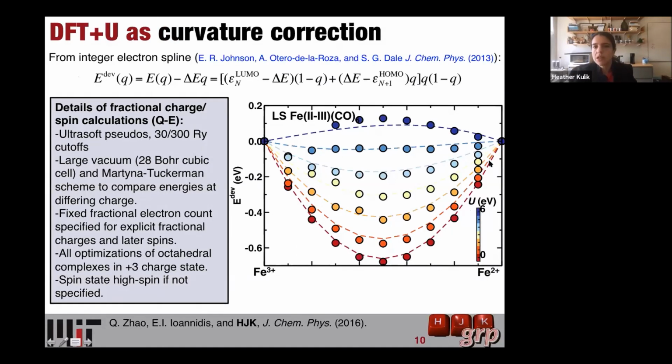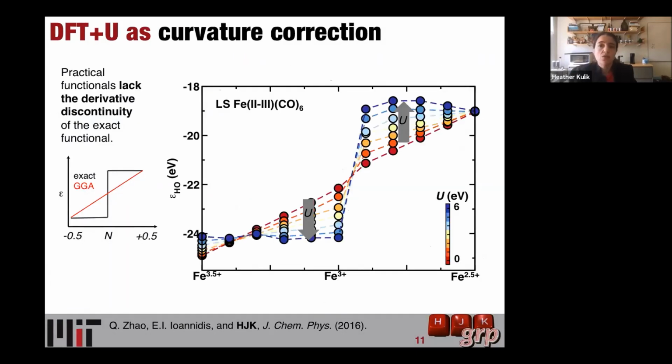Basically, once you apply the Hubbard U that gets this piecewise linearity back, here at 5 eV, you have exactly the band gap you want. Now, if you're trying to just reproduce an experimental band gap, I think you just want to do a combination of what I said, which is apply a couple of increments of Hubbard U and then see how much your band gap is changing and see if there is a U that will recover the band gap you wanted.